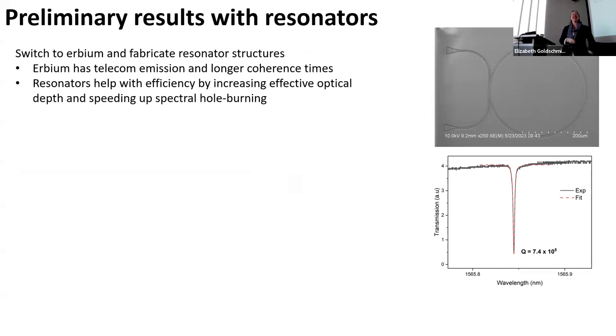So we've switched over to erbium because there are a lot of benefits of erbium over thulium. Longer optical coherence time, telecom operation, and we're making rings, cavities, which helps with everything. So if we get a little Purcell enhancement, it helps with hole burning, helps with effective optical depth. Right. And this is also going on in my lab. The other work was at Maryland with Ito.